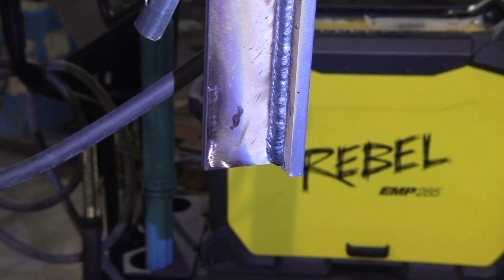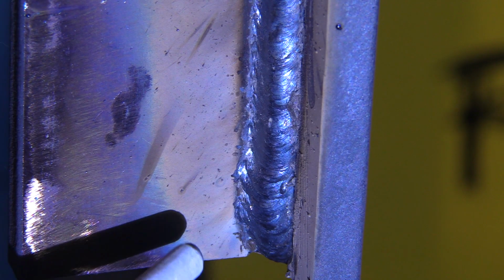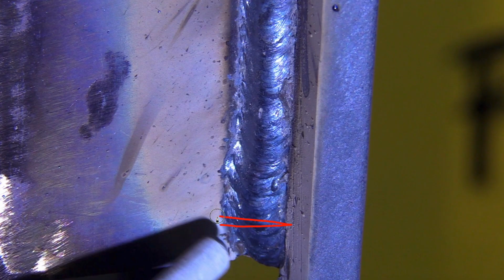Those are good restarts. So for the first half of the second pass here, we're going to do a weave pass. And in the second half of the T-joint, we'll do stringers. So one weave pass, and then on the second half, we'll stack two stringers in there. The weave pass is just basically what's called a Z-weave. Goes just about like this. Not spending much time across the middle, pausing briefly on the toes of the weld to fill in any undercut. That's the way of it.